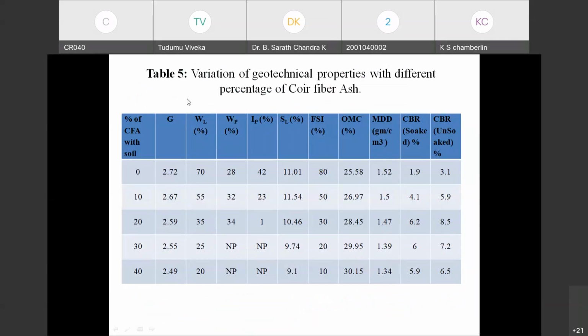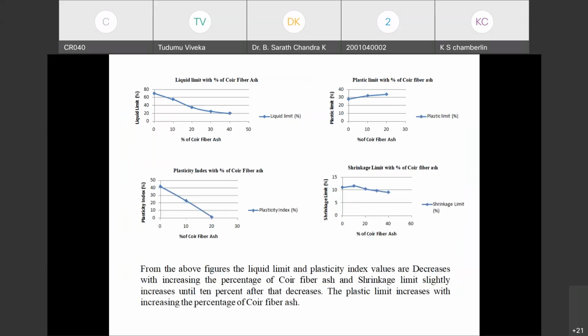And next table is the geotechnical properties of the soil with different percentages of coir fiber ash. This is the table shown here. From this figure, the liquid limit and plasticity index values decrease with increasing percentage of coir fiber ash, and the shrinkage limit slightly increases until 10%. After that, it decreases. The plastic limit increases with increasing percentage of the coir fiber ash.